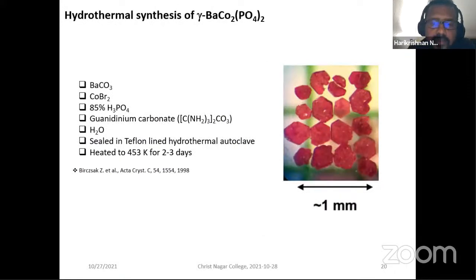So we wanted to verify that on this particular compound. The first thing is to prepare the compound, so you have to do a little bit of chemistry. This was prepared using what is known as a hydrothermal method. You start with certain precursor chemicals and mix them together at high pressure and high temperature, and you get very tiny crystal pieces. You can already see that some of them have a hexagonal shape, which is actually the shape of the lattice that the crystal adopts.